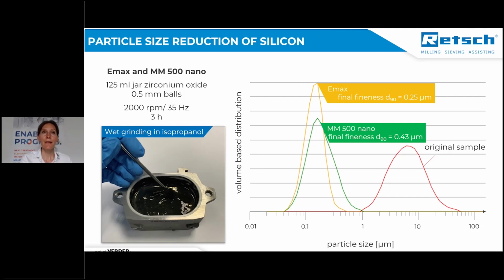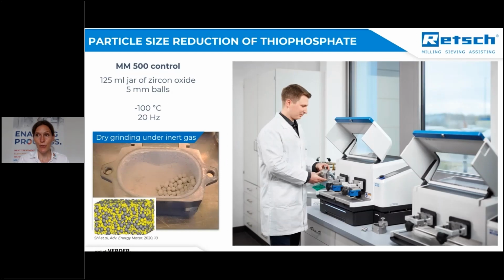Another example is the particle size reduction of thiophosphate. It was performed in MM500 control, same size of jar, 5 millimeter balls. And the outstanding property of the MM500 control is that you can control the temperature during the grinding process. So you can cool or freeze the sample during the grinding process. The thiophosphate is a lithium sulfur material, which is used for solid state batteries. It's an electrolyte, a solid electrolyte. A particle size was achieved that is optimal for dense packaging to improve the energy density of these types of materials.